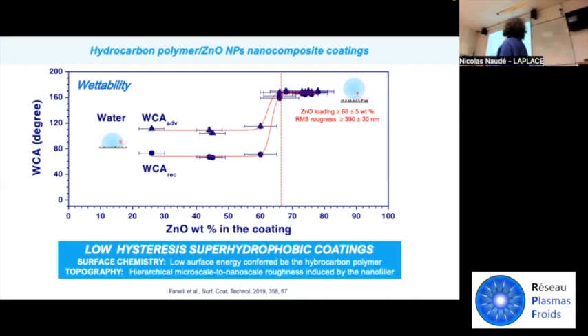Of course, this is possible. As you can see here, I've summarized the advancing and receding water contact angles of our coating as a function of the zinc oxide loading in the coating. And as you can appreciate, when the zinc oxide loading exceeds 65%, we are able to obtain coatings that show an advancing and receding contact angle greater than 150 degrees, and a hysteresis, that is the difference between the advancing and receding contact angle, less than 10 degrees. This means that we obtain low hysteresis, super hydrophobic coatings. The water droplets simply roll off these surfaces.